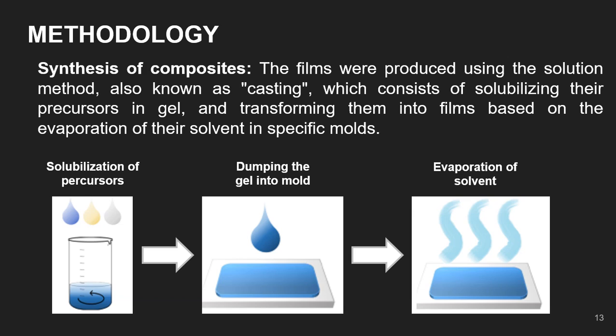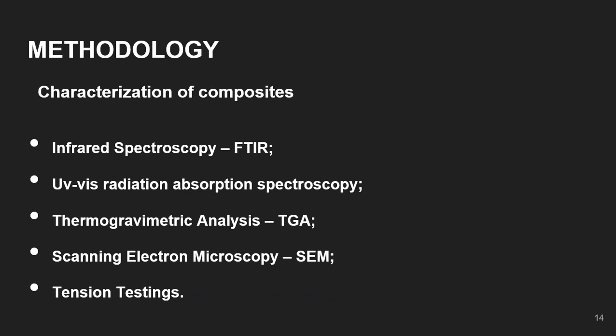For the production of the composites, the precursors of the films were solubilized under magnetic stirring until their complete homogenization in the form of a gel. Then it was poured onto specific mold plates, where its solvent was evaporated at room temperature on a properly leveled platform. In order to determine spectroscopic parameters, infrared spectroscopy FTIR and UV radiation absorption spectroscopy techniques were used.